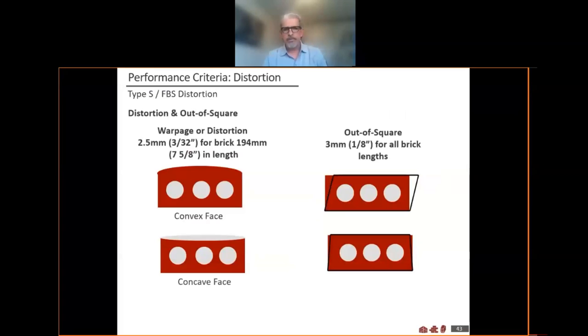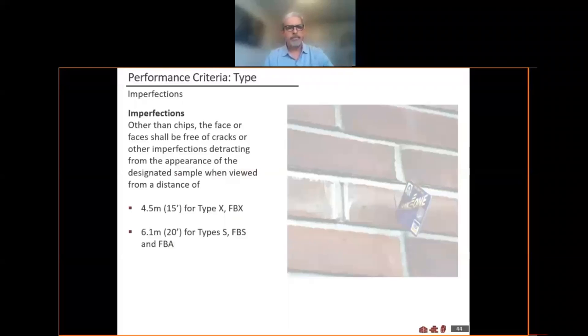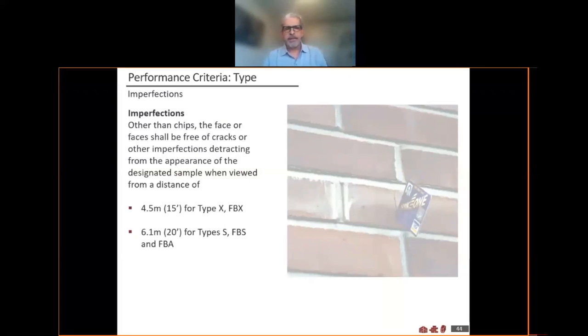That will apply as well for warpage, distortion, and out-of-square. The standard does allow for some imperfections — it addresses chippage and also cracks. One rule of thumb is that for type S, they not be visible from a distance of six meters or 20 feet. For type X, that distance would be less — four and a half meters or 15 feet.